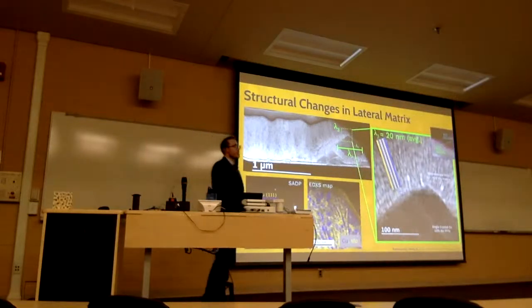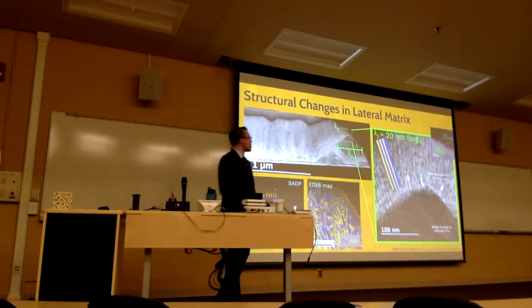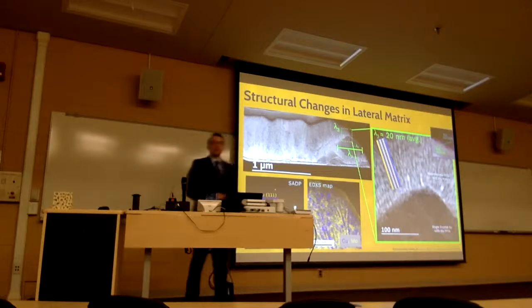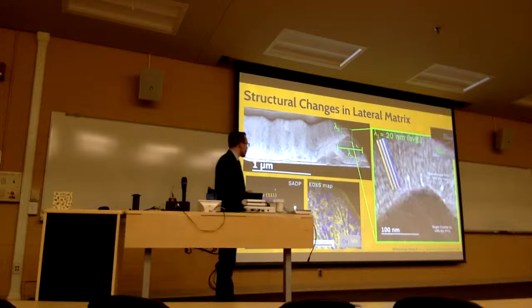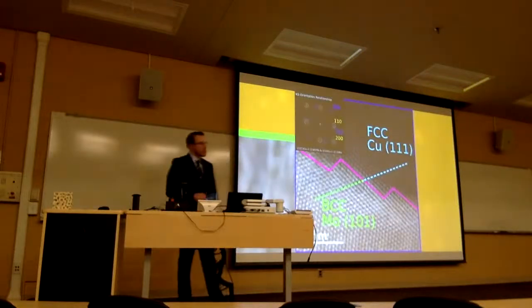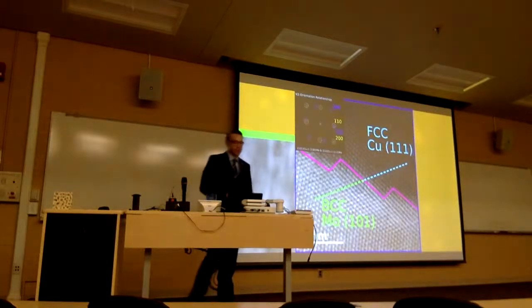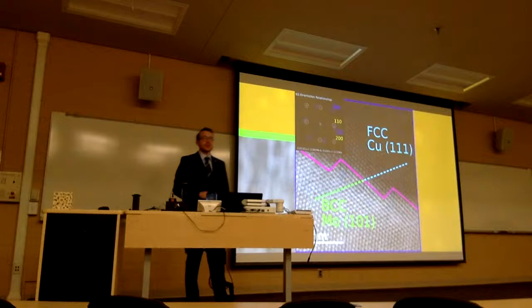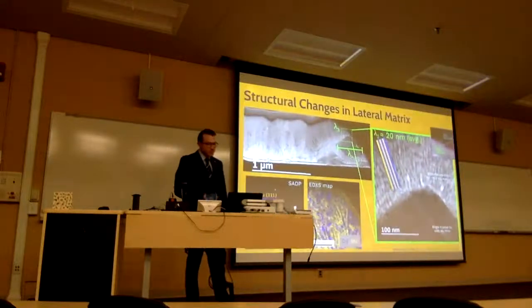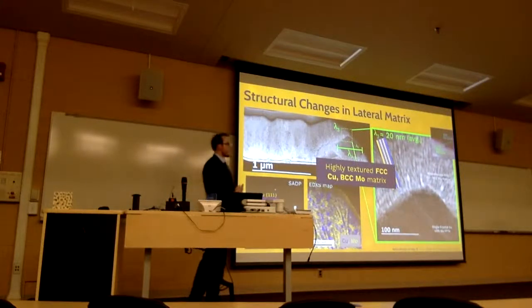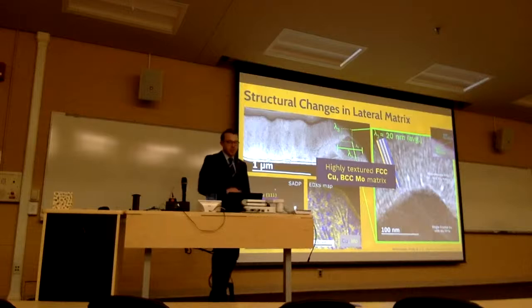The matrix is again an LCM-like morphology with lateral concentration modulations of copper and molybdenum as shown in this chemical map. By measuring the crystallography, we've achieved equilibrium copper and equilibrium moly. And if you actually look at the interface between those two crystals, you can see that we've again designed a semi-coherent interface between the two crystals in a Kurdjumov-Sachs orientation relationship. So in here we have a highly textured FCC copper BCC moly matrix.